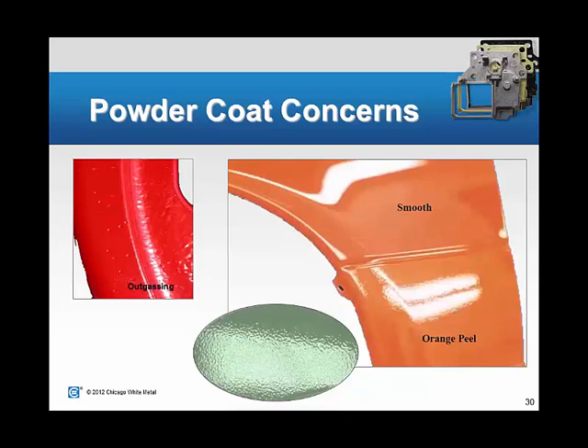Another thing that is common is an orange peeling condition. You see the image on the right shows a nice smooth part above, and then the orange peel, which almost feels like a texturing. That is an over thickness of powder that's applied. This occurs many times when you're trying to apply powder to a deep recessed area in a part, and the features above will get more coating because of that. So again, it's just something to think about in advance. By changing the way parts are going to be racked, you can minimize this.